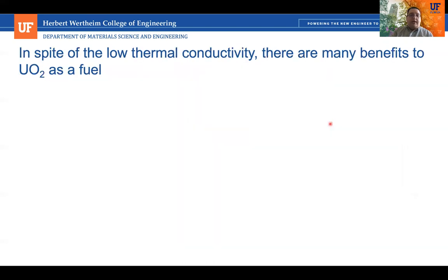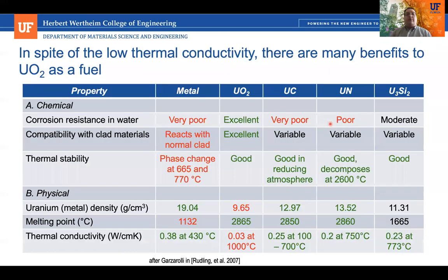Now, UO2 has other good things about it. The main reason it's been selected is because of safety issues. So everything related to safety is quite good when you compare against other uranium-bearing materials. It has excellent corrosion resistance in water, which is the coolant. It has good compatibility with the zirconium cladding material. It has great thermal stability, so it's not changing phase or having drastic changes in shape or anisotropic thermal expansion or anything like that. And it has a very good, very high melting temperature. And so you can get to high temperatures.